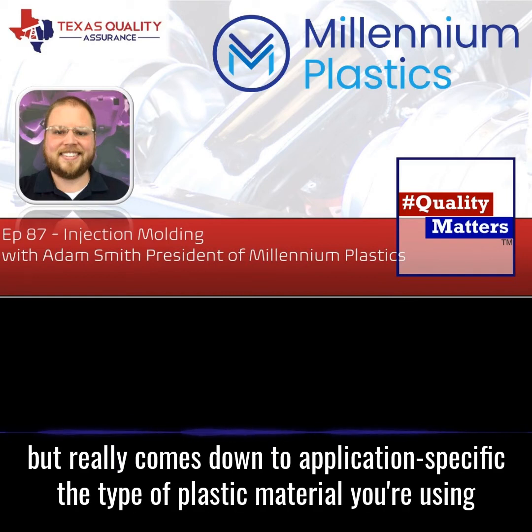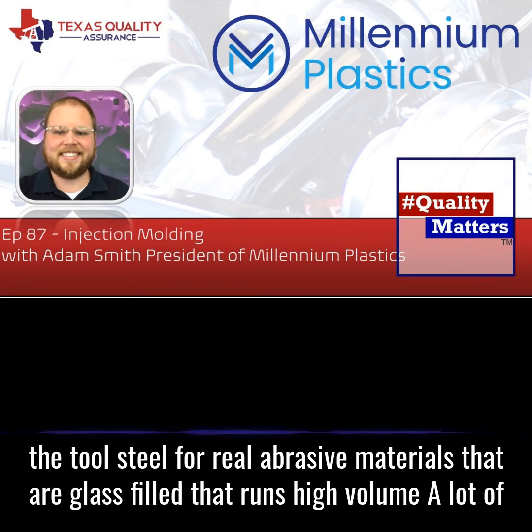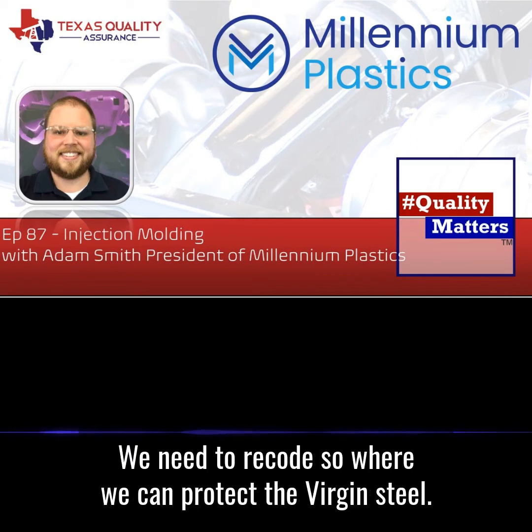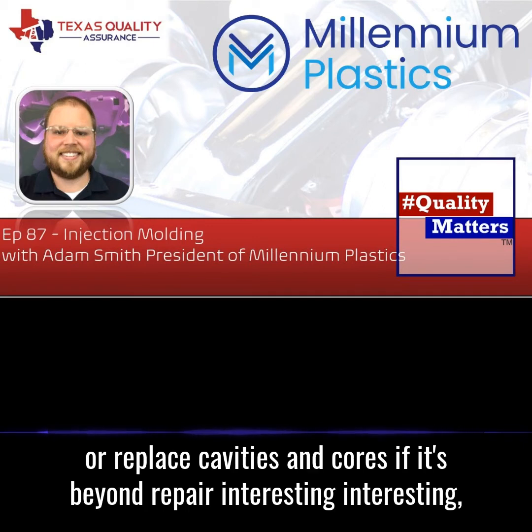But it really comes down to application specific, the type of plastic material you're using. If it's really an abrasive material, you start getting into coating the tool steel. For real abrasive materials that are glass filled and run high volume, a lot of times we will double coat it with a different colored coating, so you never get back down to virgin steel before you realize, hey, this coating's wearing off and we need to recoat to protect the virgin steel, so we don't have to weld or replace cavities and cores if it's beyond repair.